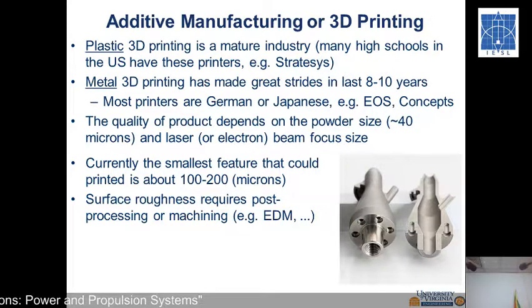Now the resolution depends on the laser, what you call the focus beam, right? I was told the smallest feature you can print currently is about 100 to 200 microns. I have printed a part with a 150 micron orifice that can be printed with this Inconel material. Okay. Now there's one problem though.